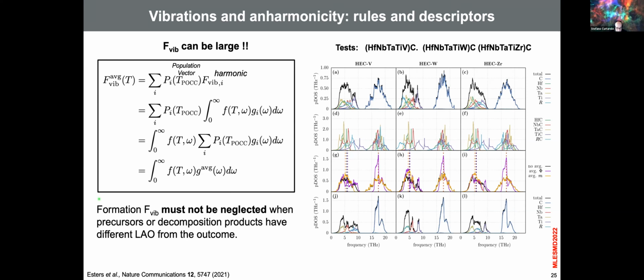Practically, if you are studying thermodynamics, excuse me, and your precursors, remember the precursor, you need to study the precursor and all the subcomponents that create the decomposition of the final product. If they all have the same local atomic environment, which is something that can be calculated, Hagen is writing the code to calculate the atomic environment automatically for all our database. So anyway, if you start from the outcome, if the outcome minus all the decomposition to the precursors all have the same local atomic environment, you do not need to calculate vibrations, because they will all cancel out, right? Same atomic environments, similar vibrations, they cancel each other, because you are dealing with formation energies, formation vibrational energies. So since there is this word formation, they cancel.